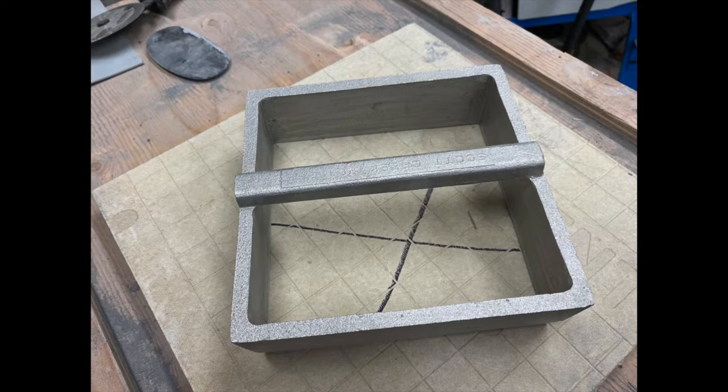One thing to remember when creating a design is that clay shrinks a fair amount during the drying process. This shrinkage varies with the clay body you have chosen. But if you want to be exact, you'll need to fire a measured sample of the clay you're using first. The low fire clays I use seem to shrink about 4 to 5% when fired to cone 06.